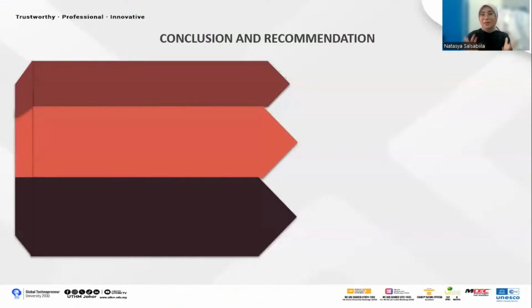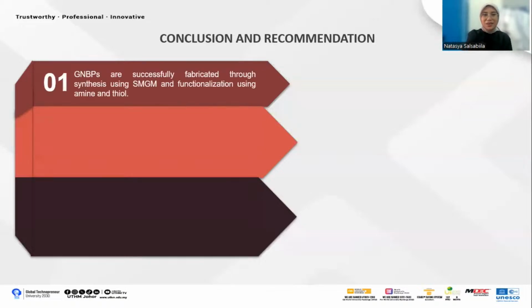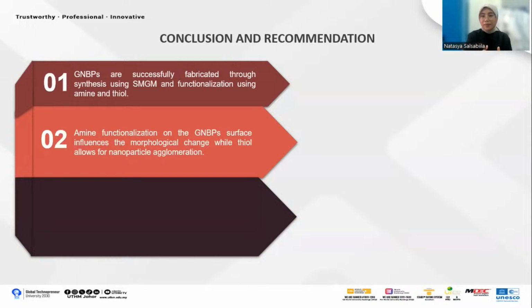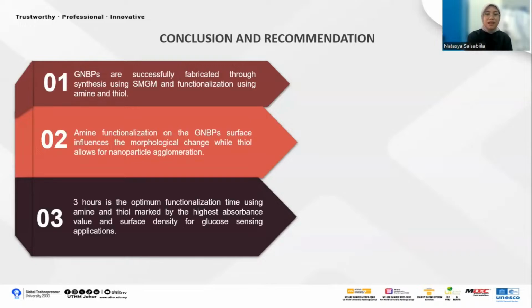Okay, now I will summarize the whole discussion. Overall, gold nanobipyramids have been successfully synthesized using SMGM and functionalized using amine and thiol groups, with amine influencing the morphological change and thiol influencing the nanoparticle agglomeration. Based on characterization results and plasmonic response testing, 3 hours is the optimum time to modify, or to functionalize, the surface of gold nanobipyramids using amine and thiol groups.